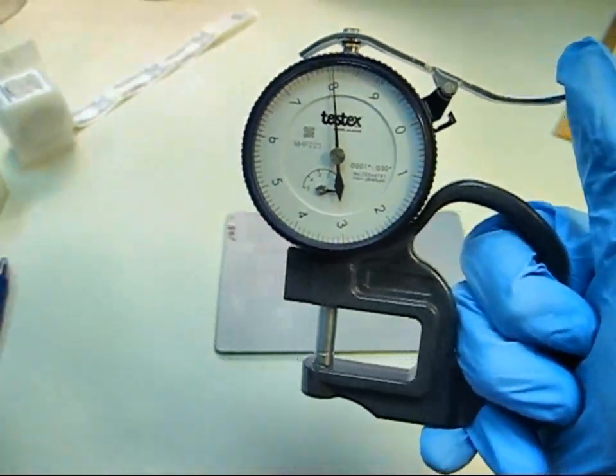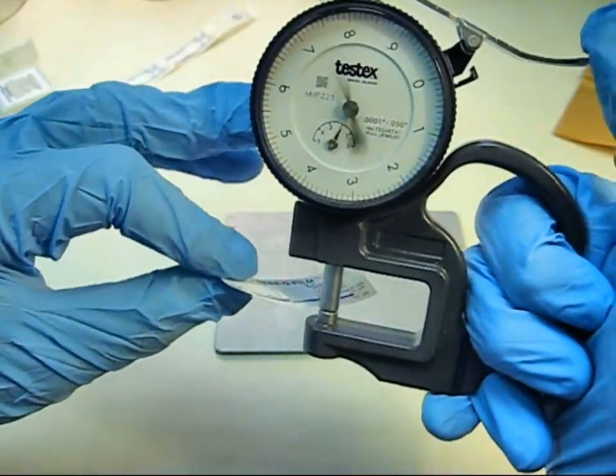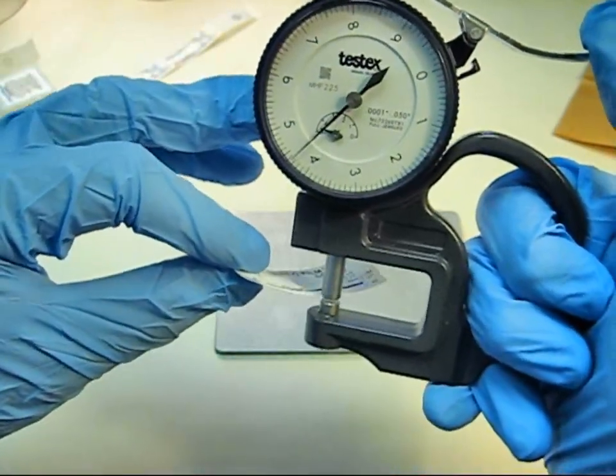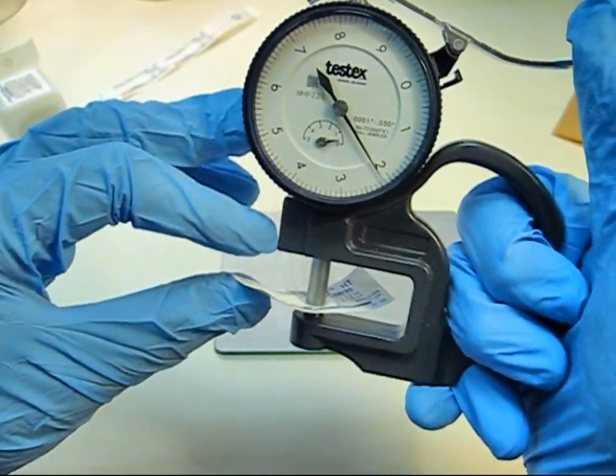Now, remove the replica and place it centered between the gauge anvil and the contact surface. The gauge reading is a measure of the peak-to-valley roughness, or profile.